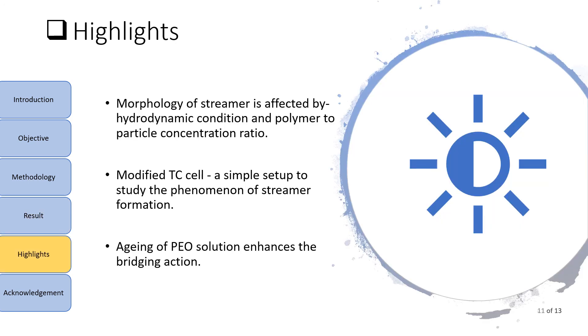Now I would like to conclude this presentation with the following key points. First, morphology of streamer is affected by hydrodynamic condition and concentration ratio of polymer to particles. Second, a Taylor Couette cell with some modification can be used as a simple setup to study the phenomena of streamer formation. And third, aging of PEO solution enhances the bridging action shown by these polymer molecules.